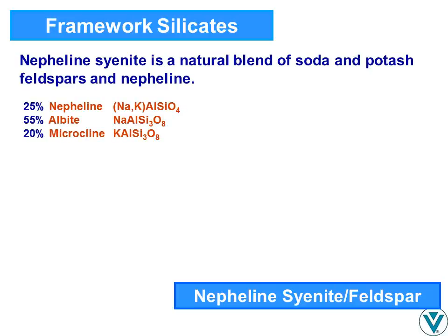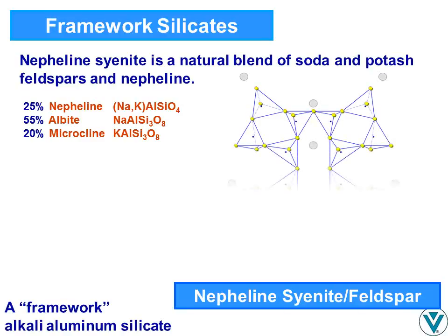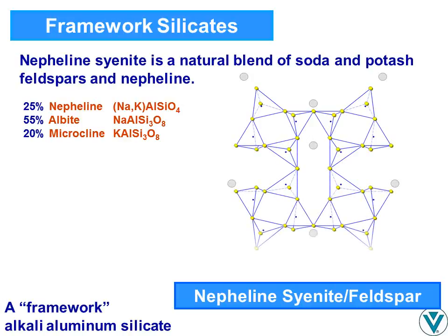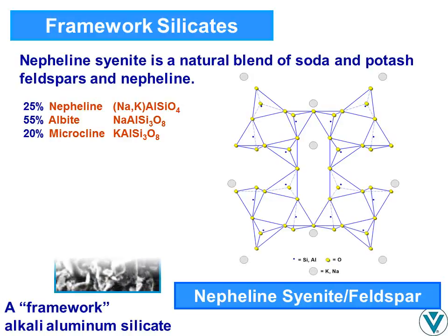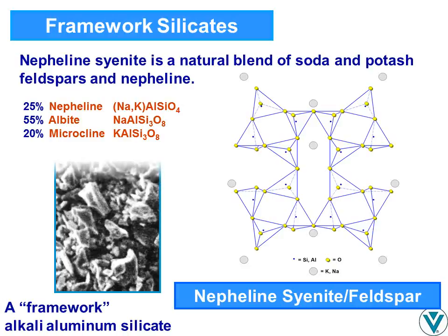Feldspar mineral structures are based on densely packed four-member rings of silica tetrahedra, forming hexagonal and polygonal voids. The dense packing makes feldspar nearly as hard as quartz. Typically, Al3+ replaces one of every four Si4+, and the resulting charge imbalance is compensated by sodium and/or potassium ions. Nepheline shares the feldspar structure, except that Al3+ replaces half the Si4+. Unlike feldspar, the sodium ion in nepheline can be exchanged with hydrogen ion, making nepheline less acid-stable. Nepheline will gelatinize in HCl, while feldspar will not.